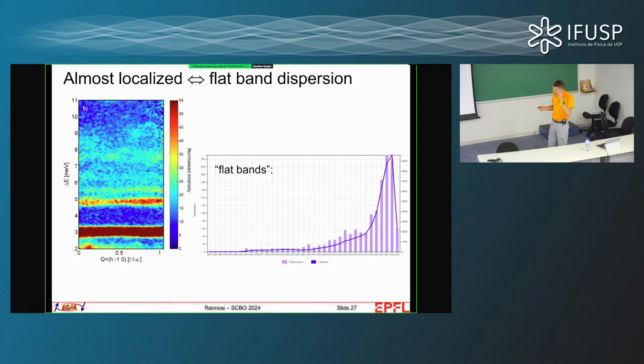And so if you have something that is local in real space, in reciprocal space, it means that it's independent of momentum. So in other words, you have an excitation with a finite energy, but that energy is independent of momentum. In band structure, we like to call that a flat band, and there's quite a bit of interest in flat bands, for instance, in twisted bilayer graphene and others.